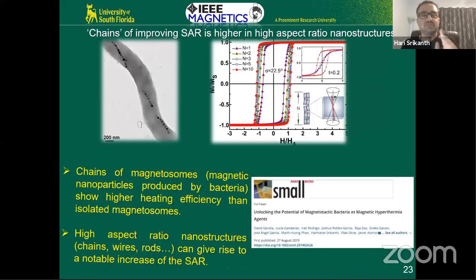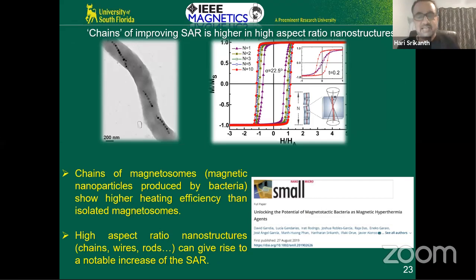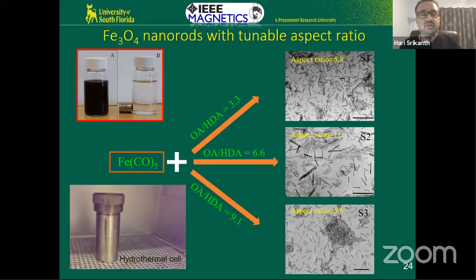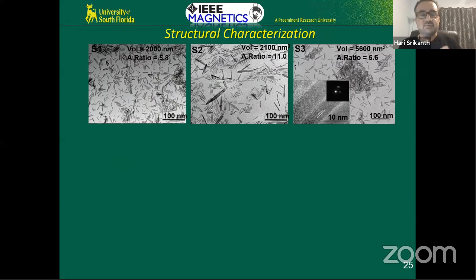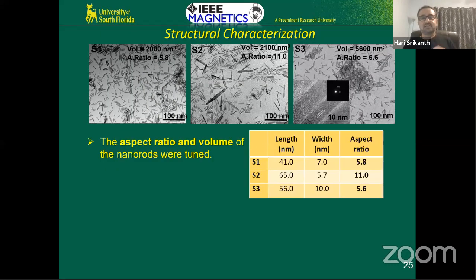Let me go towards the closure now, because I'm going to skip a few slides. I know that I'm running late. So let me just go to, we can also make these nanorods, and we do that by the so-called hydrothermal technique, like a pressure cooker. It's a pressure cell. In addition to temperature, time, and the surfactants, we introduce pressure also as a variable here, which controls the growth of the particle. So you can make these beautiful nanorods. And these were done by Raja Das, another postdoc.